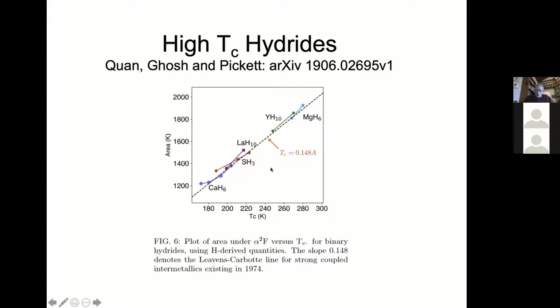This plot here is actually from this paper from Warren Pickett and co-workers, the so-called Leavens-Carbotte plot, where you take the area essentially of alpha squared F. This is for the hydrogen derived quantities, and you see that there's actually a rather interesting parallel between this area and TC, and you can think of this as having to do with a kind of competition between hydrogen bonds and not.